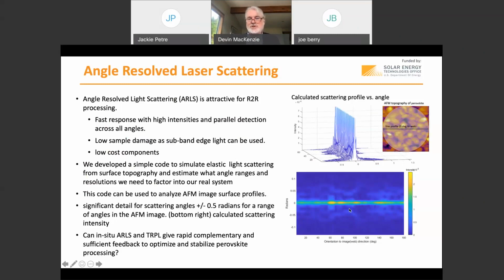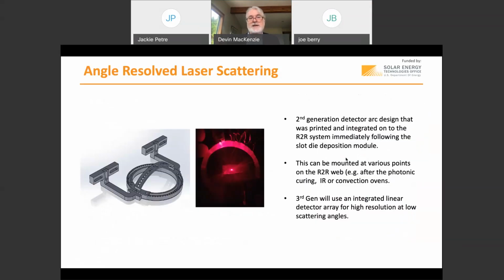Again, this is just trials, not meant to be numerical, but it shows that probably within half a radian is where most of the interesting things are happening, so we use that to refine our angle-resolved scattering, our ARS scattering rigs. We started off with a simple prototype where we could mount a discrete, large-area photodiode, because we thought we'd be starved for signal, and we proved that worked, but it didn't have enough resolution at those low angles. So we've now moved to a linear detector system, with a linear detector at low angles, so we can get better resolution at those low angles.